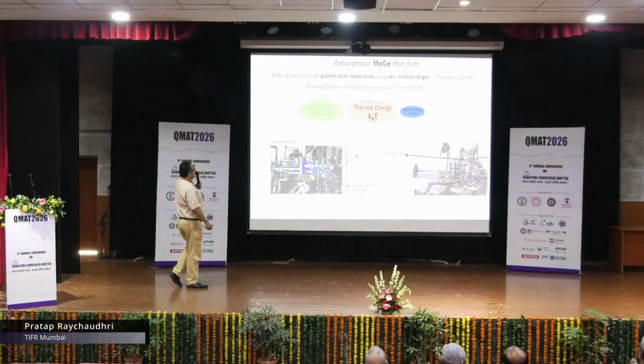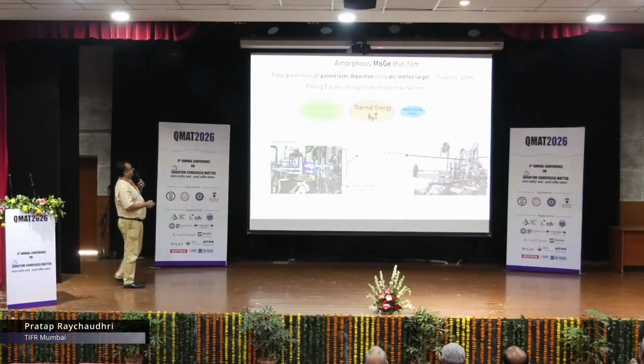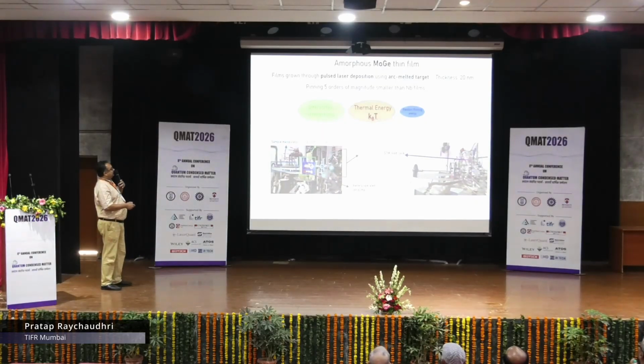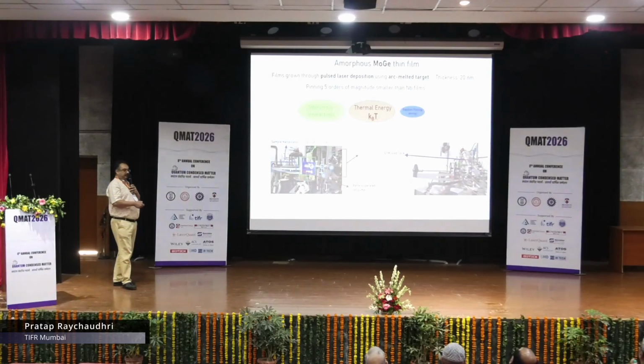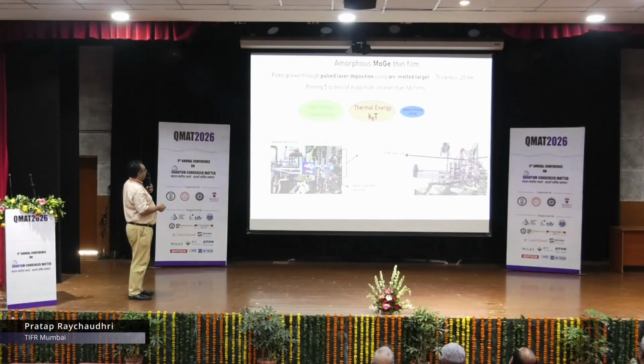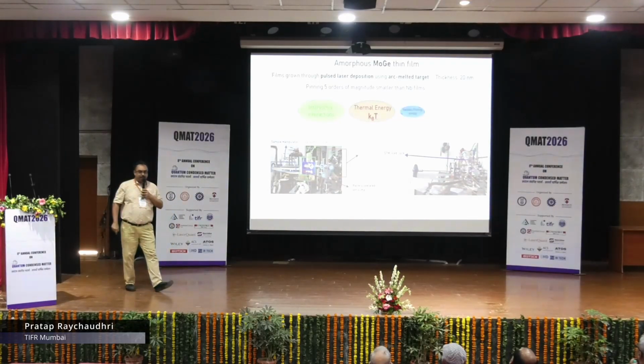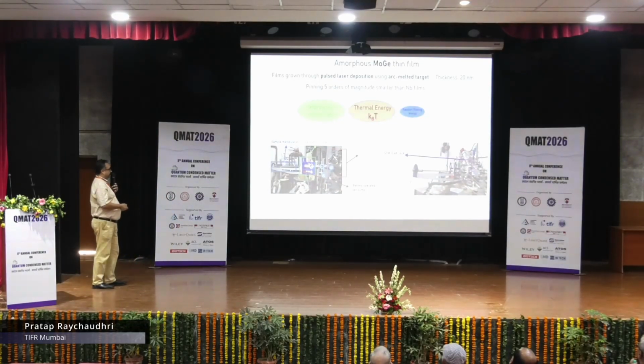So to verify that, some years back, we started investigating amorphous molybdenum germanium thin film, where we can make, of course, very thin films with moderate TC of 7 Kelvin or so. But in addition, here the pinning is very small. So the energy scales in the problem will be intervortex interaction and thermal energy, with this random pinning energy being secondary. So it's not a major player here.